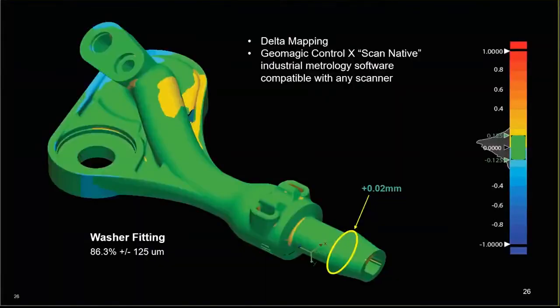For accuracy measurement, we use Geomagic Control X — we scan the physical plastic part, register it back onto the STL file, and generate a heat map showing deviation from nominal. This gives you a visual on the global accuracy of the component and is a very useful tool for problem solving and quickly assessing tool capability for plastic part production.